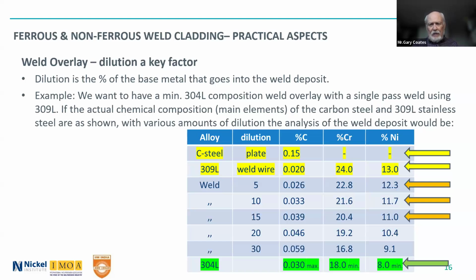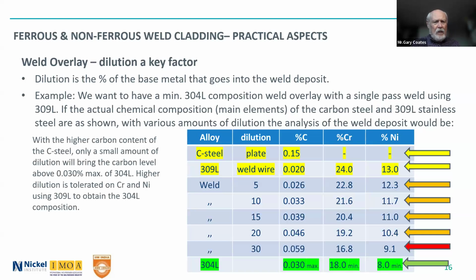At 15% we're getting more dilution, more iron into it, so the chrome and nickel are getting lower, still acceptable. Carbon is getting a little higher. At 20% dilution, higher carbon, and here both the chromium and the nickel are actually within the limits of 304L. And if we do 30% dilution, all of a sudden we have too low chromium content. So it definitely is not 304L minimum composition there. So dilution is a key factor.